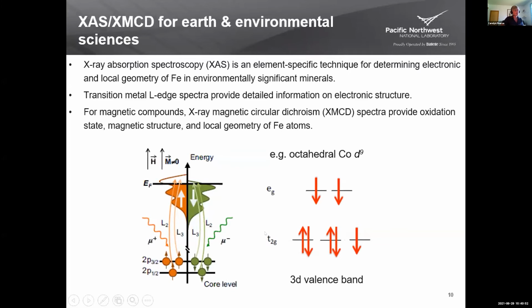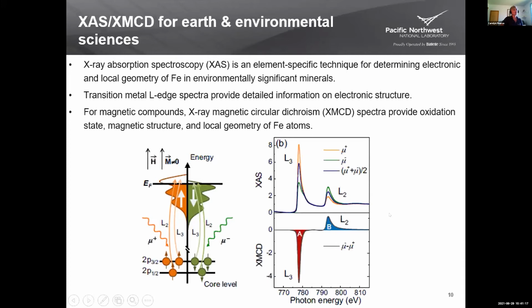In the second step, the excited electron has to then move back down and find its place in the 3D, in the unoccupied 3D valence band. And that depends on the electronic structure of the material that you're interested in. So it's that excited electron trying to find its space in the valence band that gives you a probe of that valence band structure. This is what the spectra look like.